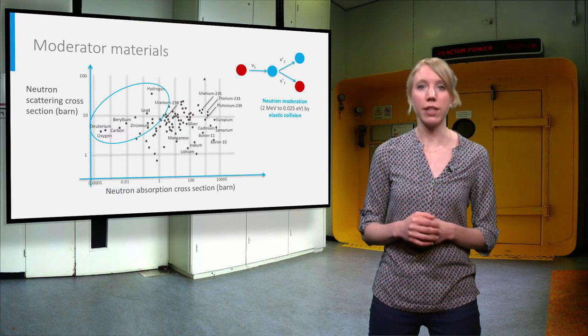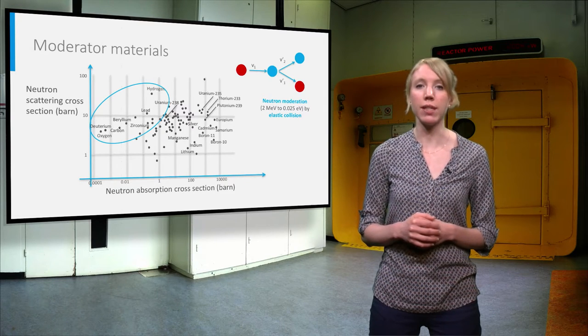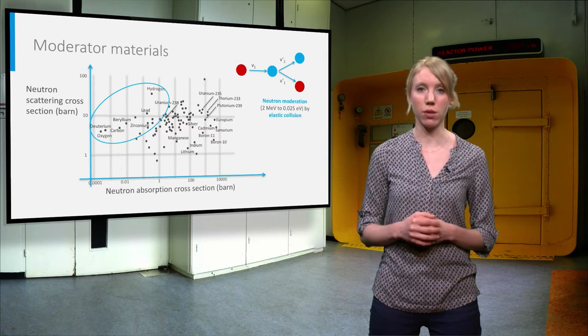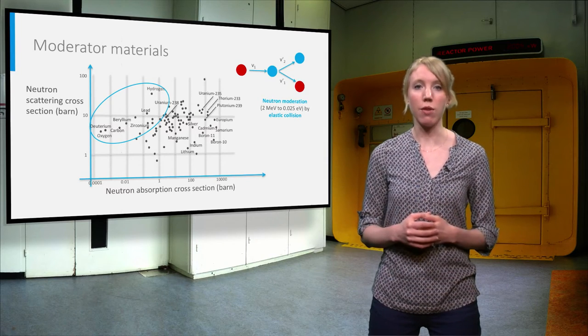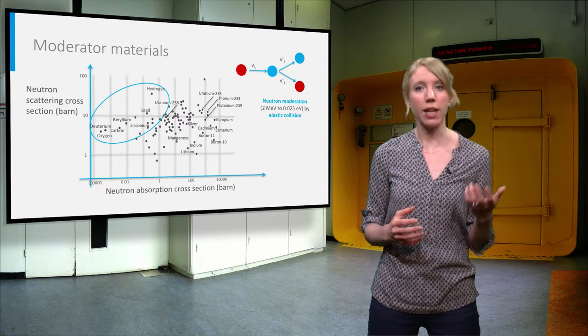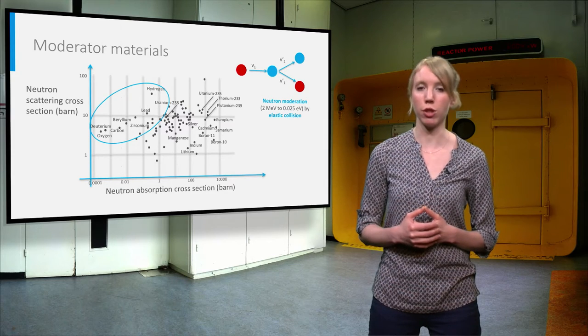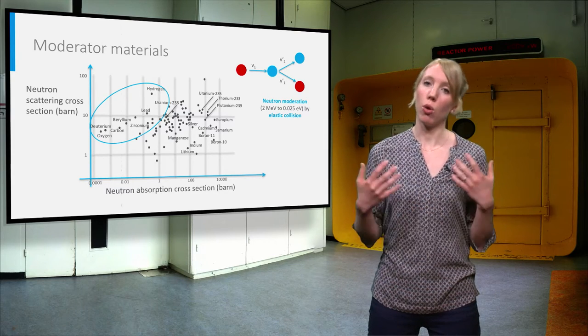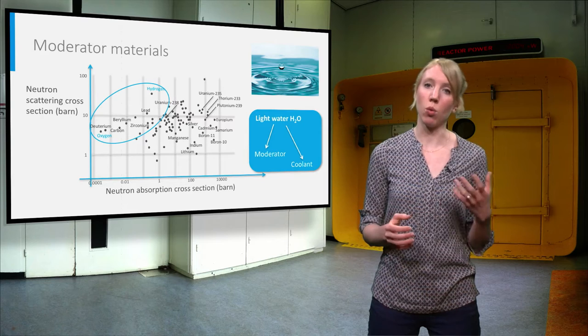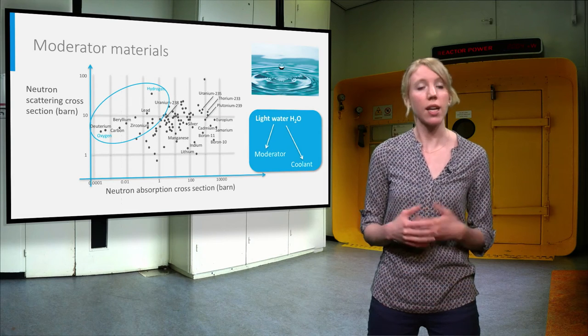In addition, the effectiveness of the moderation depends on the mass of the nucleus. Good moderators have a low mass because in that case less collisions are required for moderation. The most used moderator is water, which also acts as a coolant.